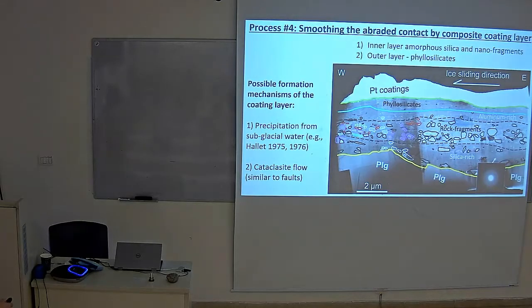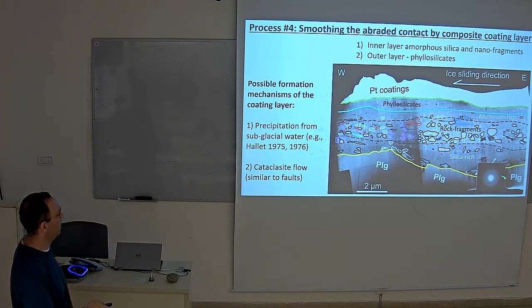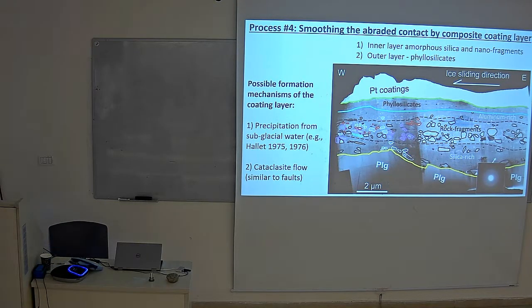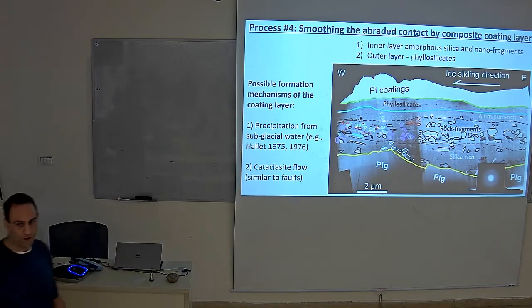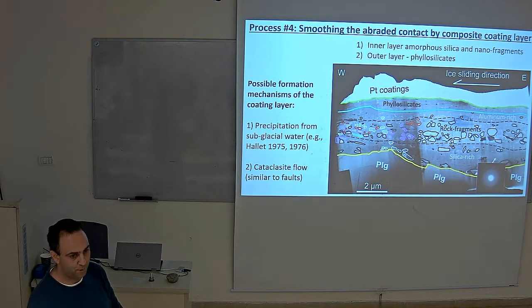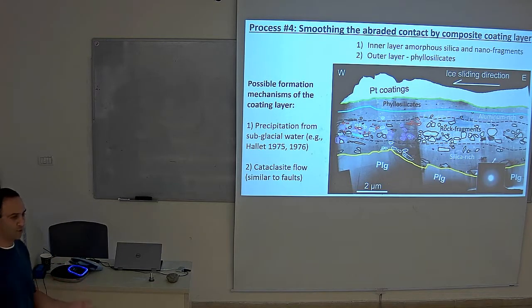And we get a coating layer now, a continuous coating layer. We see an inner layer of amorphous silica. Here is the amorphous structure, no structure, this is amorphous with X-ray diffraction in TEM, and an outer layer of phyllosilicates with many fragments inside. Now, the bottom is a plagioclase crystal of the original bedrock, of the granodiorite, and the fragments are different. They have quartz, feldspar, plagioclase, and they represent a mixture of the original granodiorite.